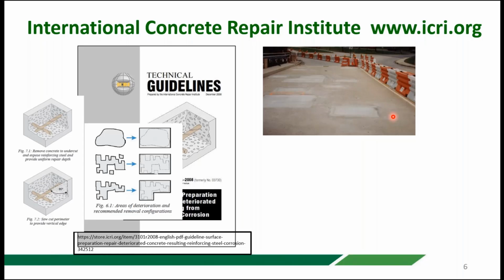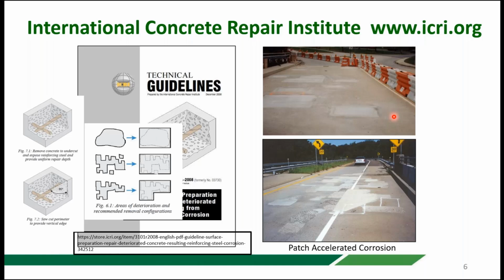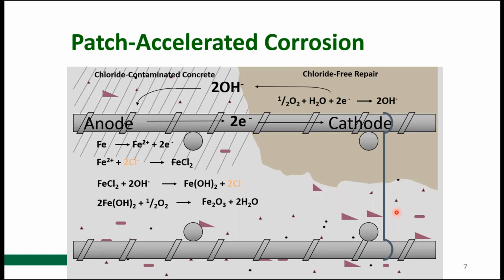But the issue, if you do good quality repairs, you can make the repair itself last, but that doesn't mean the overall structure is going to last, because if you do this type of repair, even if you do good repairs, you can run into a situation where the area adjacent to the repair continues to corrode, and you end up going out and doing more repairs and then come back and do more repairs. And we refer to that as patch accelerated corrosion. And so even though the repairs themselves might be done well, you can still have an ongoing corrosion problem that causes a maintenance issue. And why does this happen?